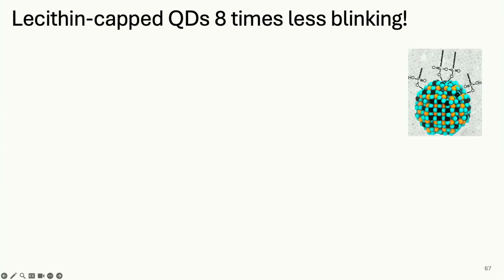But they have a problem that is referred to as blinking, where they will be emissive dots for a while, and then the dot will not emit for some time, and then it'll go back to emitting. And it's thought that this relates to defect trapping, that if you have a trapped hole and a free electron, then that electron gets involved with other carriers and facilitates them losing their energy non-radiatively. And so the idea is if we can remove the defects, we're pretty sure we can reduce the blinking. And so the experimental observation is that using lecithin, capping the quantum dots leads to much less blinking.